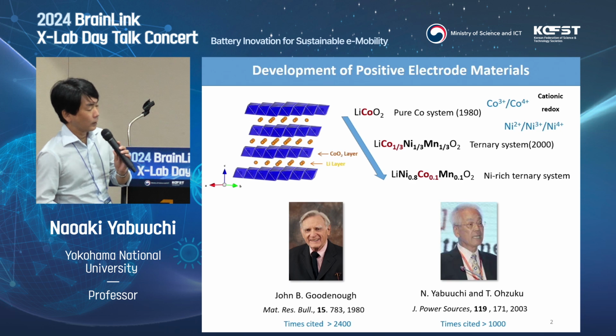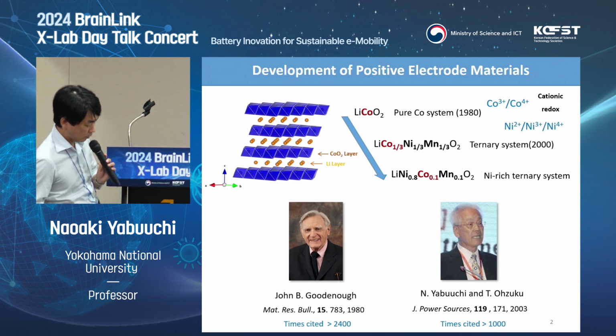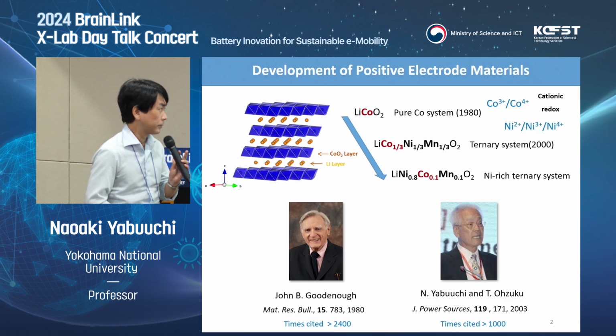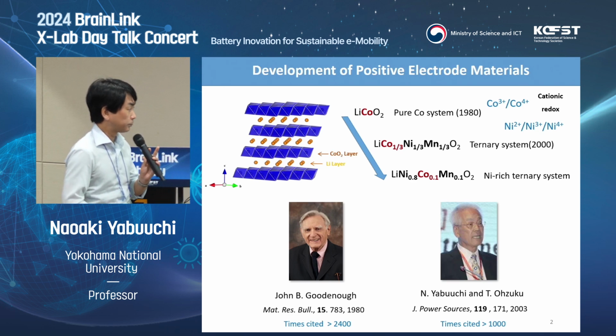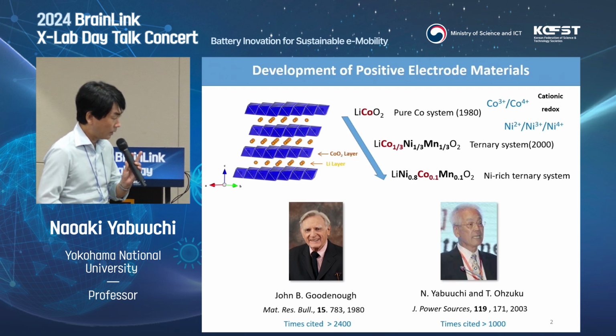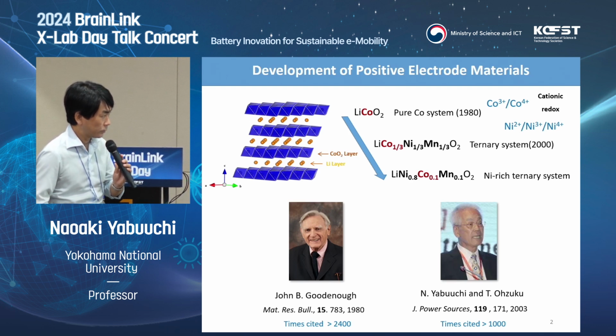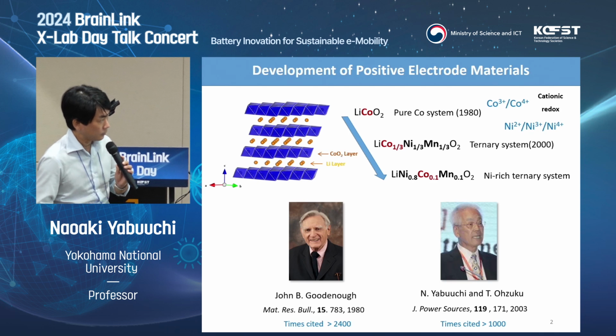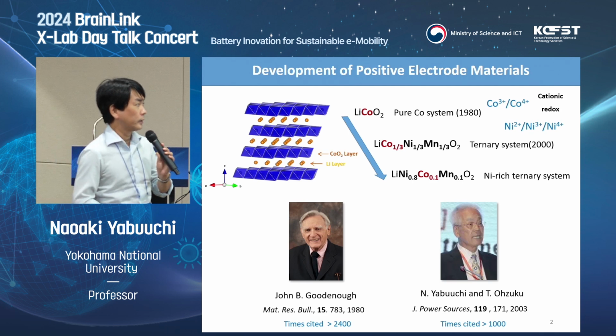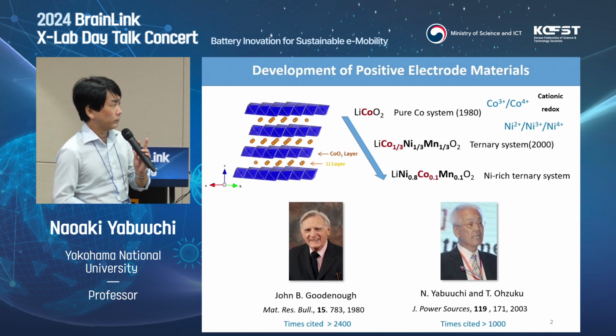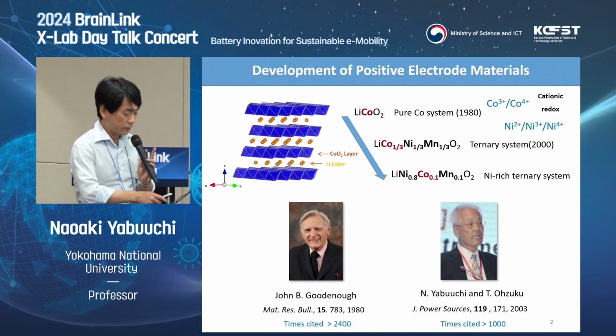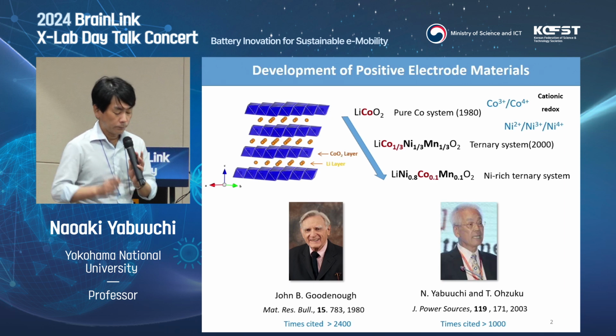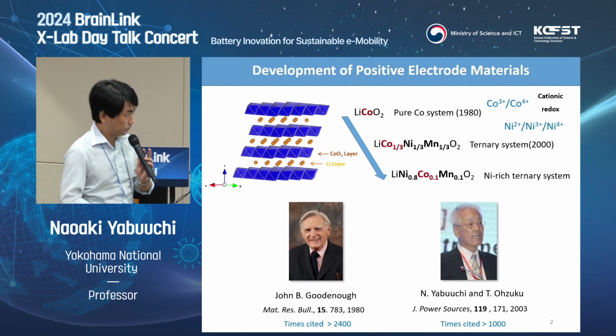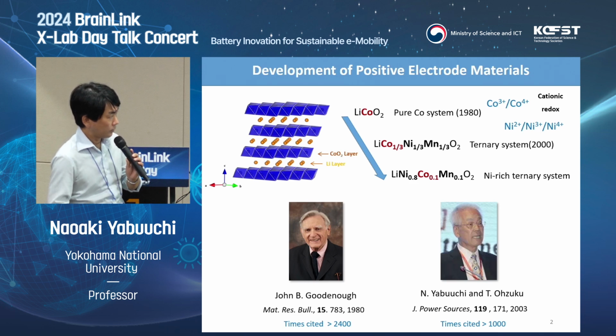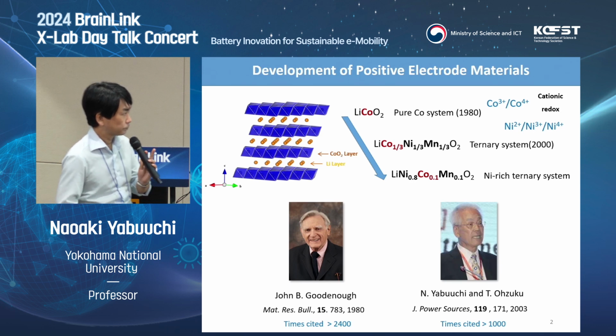Historically, the lithium-ion battery started from lithium cobalt oxide. Cobalt is, of course, a very, very expensive element. So to reduce the battery cost, my former supervisor from my PhD days, Professor Ohzuku, developed the cobalt 1/3, nickel 1/3, manganese 1/3 system in 2000, the so-called ternary system. Now the cobalt content is reduced to only 1/3 of the original composition. And state-of-the-art electric vehicles use lithium nickel-rich systems, for example the 8-1-1 system, so the cobalt content is reduced to 10%.